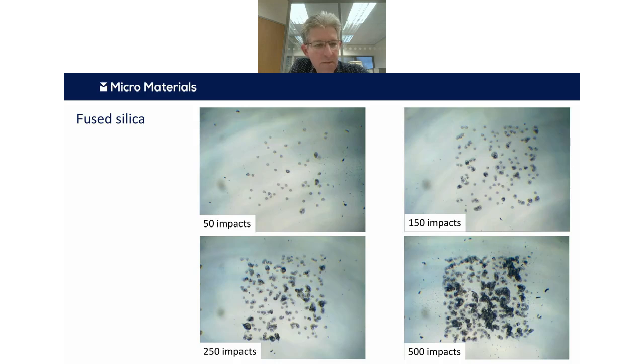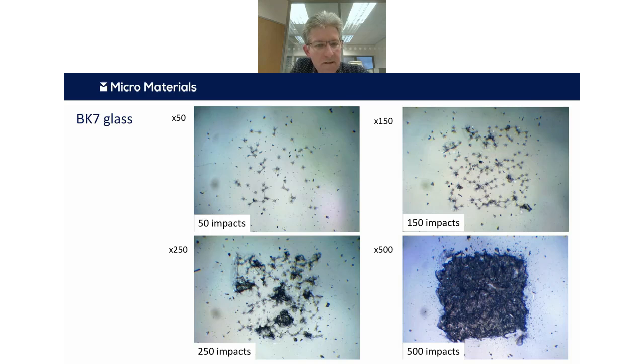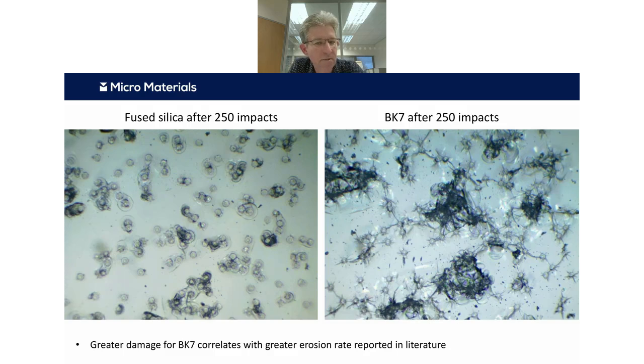Something more dramatic happens when you look at the BK7 glass, and you can see here, even from 50 impacts, we're starting to get networks of cracks already forming between some of the adjacent impacts. As we run this test on with more impacts, these networks build up, and these are leading to rather dramatic removal. And at the end of the test, we've just completely destroyed the sample. So this is quite a nice result, because this correlates with what you see in the literature for erosion resistance: despite the fracture toughness, BK7 does have a worse erosion resistance. And although the size of the impacts in both cases is about the same, the crack morphology is really quite different.